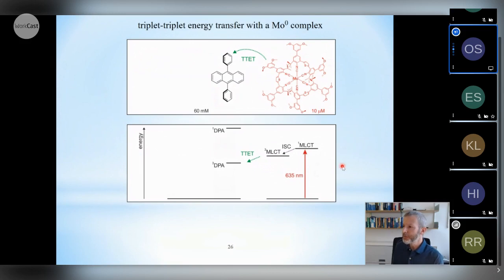And this design principle led to a situation where Jakob is now able to excite these compounds in the red spectral range. That had not been possible before. Our previously studied compounds resemble a lot ruthenium tris-bipyridine. This new compound resembles a lot osmium tris-bipyridine. So when Jakob excites that compound into a singlet MLCT, there is rapid, presumably ultra-fast and quantitative intersystem crossing to a triplet MLCT, from which triplet energy transfer to diphenylanthracene here can occur.